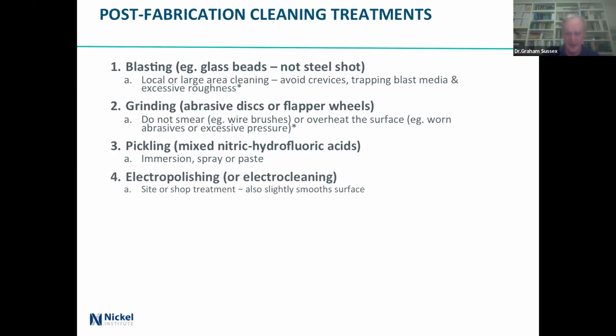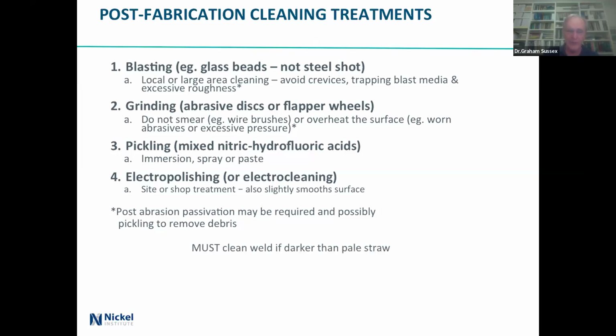Electropolishing or electrocleaning, this is the TIG brush that I was talking about. Both of those will slightly smooth the surface and give you a very bright surface too. And the little stars up there, if you've got a rough surface, you may need to post-abrasion passivate it. That's passivate nitric rather than passivate and pickle. Or maybe you have to pickle it because you've got to get rid of debris.